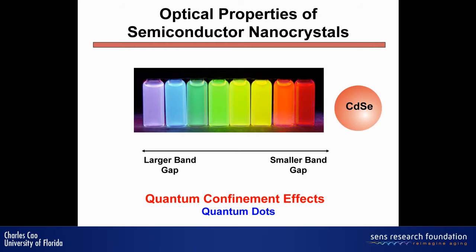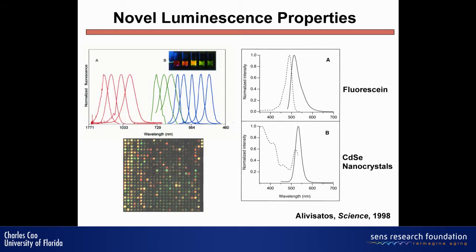This quantum confinement gives unique properties to many quantum dot crystals. These particles, because of their unique fluorescence, can easily generate many unique labels — from ultraviolet to the visible and near-infrared. I can generate multiple markers to label multiple targets. Compared to organic molecules, the emission spectrum of nanoparticles is narrow. The excitation spectrum is continuous, and you can use one laser to read all these labels simultaneously. With organic dyes, you have to use multiple lasers, which increases the complexity of the reading setup.